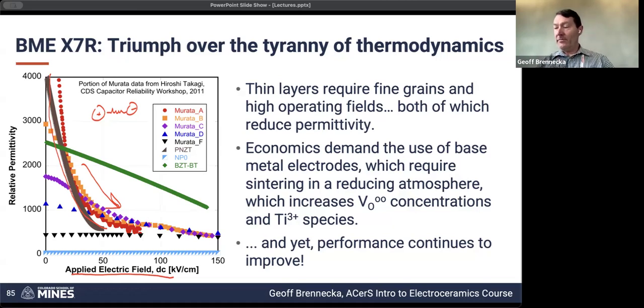And on top of that, as I mentioned before, we also need to do this with cheap enough electrodes that we can sell these things. So we talked about defect chemistry a lot earlier this week. If we're going to co-sinter with nickel electrodes, we have to do this at a very low partial pressure of oxygen to avoid oxidizing the nickel. Because a nickel oxide electrode is not conductive enough to be an electrode.